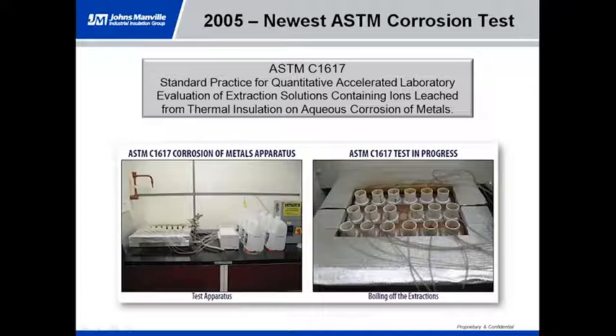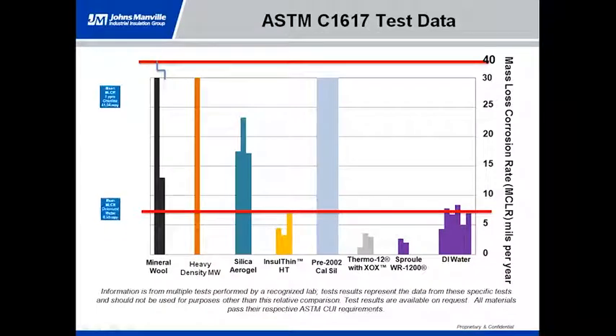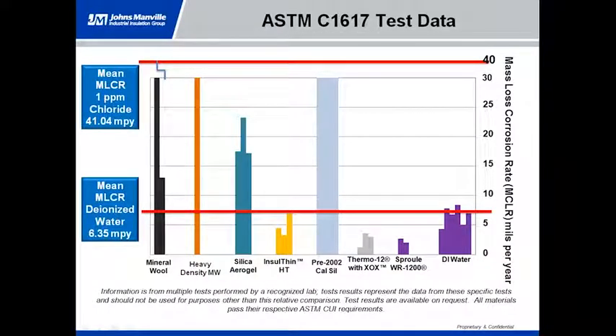Now, once the test is run, and it's run for 96 hours, those coupons are cleaned and then they're weighed, and then that change in weight is used to give you a mass loss corrosion rate in mils per year, or an MCLR. Whenever we run this test, just to make sure that you're not running it in a vacuum, you always want to make sure that you have some control that you're using as a reference point. There are 3 that are typically used, and 4 that are available. One is DI water, or deionized or distilled water, which has less than 0.1 part per million of chloride solution. There's a 1 part per million chloride solution and a 5 part per million chloride solution. So the higher the concentration of the chloride solution, the higher the corrosion rate.